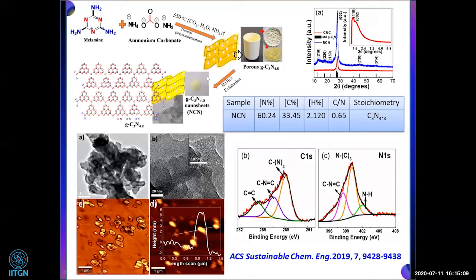That was the synthesis. What we got, the important point is that we have a nitrogen rich compound. We have excess nitrogen. The general formula is C3N4, but we have C3N4.8. How do we characterize the excess nitrogen? We found it from the XPS.